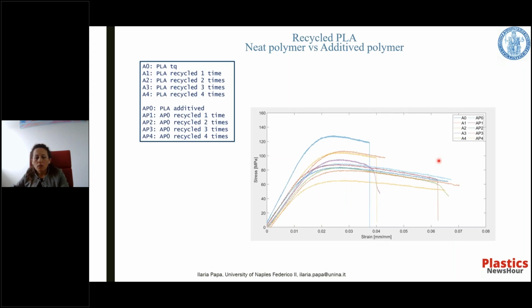In particular, we have evaluated the effect of adding a chain extender, that is a peroxide, to PLA subjected to various mechanical recycling. So we have the neat PLA materials recycled 5 times, the neat one recycled 1 time, 2 times, 3 times, 4 times, and also the additive ones recycled 1 time, 2 times, 3 times, and 4 times. And in this case, we have recycled the PLA filament and reutilized it in the 3D printing, and realized also the additive filament for the 3D printing, recycled it 5 times.